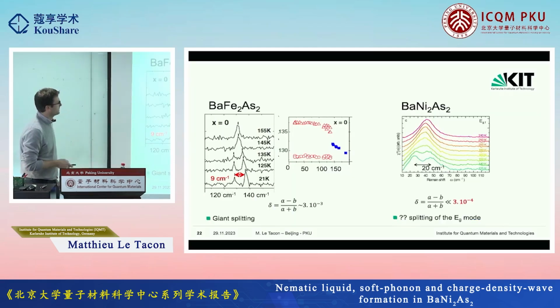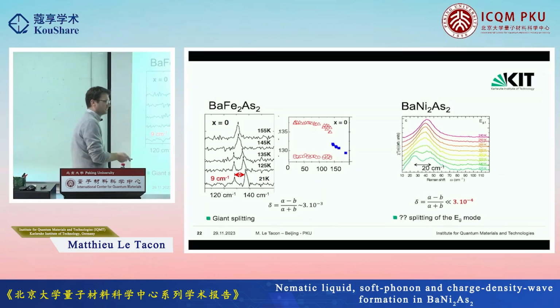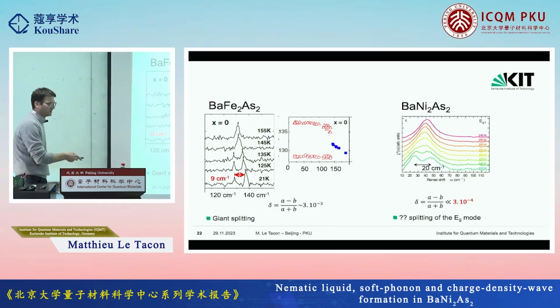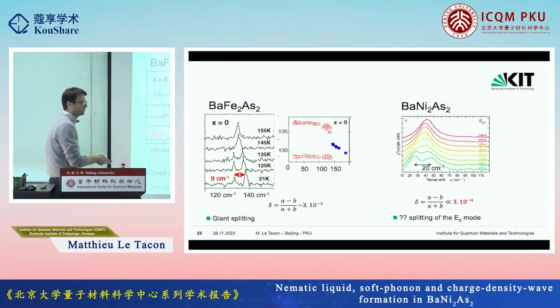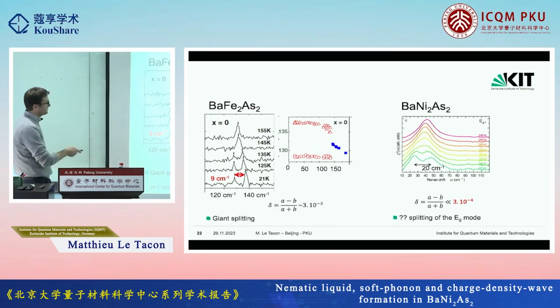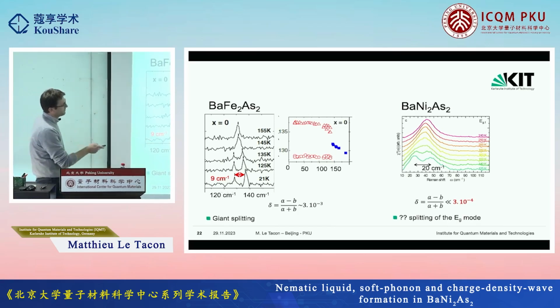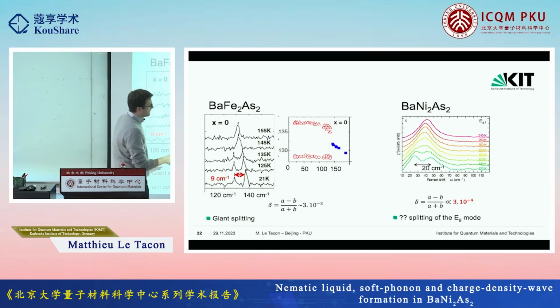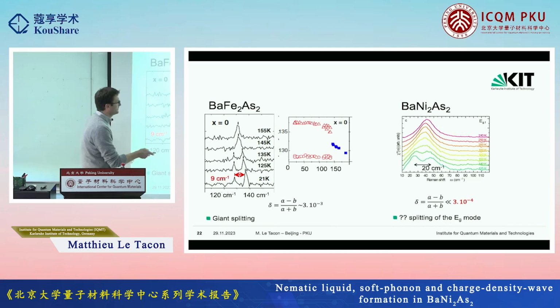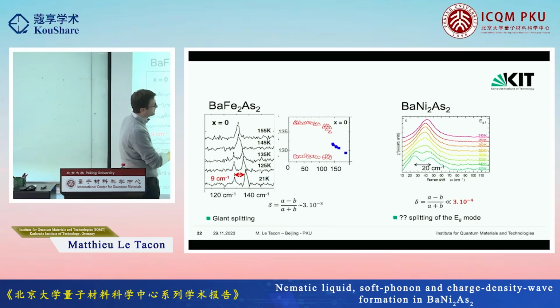Let's look at the numbers, because on the BaFe2As2, I had an orthorhombic distortion of 3 times 10 to the minus 3, that's the difference between a and b, so 0.3%, and I had a split of 9 wave numbers. In this BaNi2As2, I have a distortion which is at least 10 times smaller, but my splitting is at least twice larger. And if I look at the relative splitting, the phonon here is quite soft, it has a frequency of 40 wave numbers, I have a splitting of 50% of the mode's frequency.